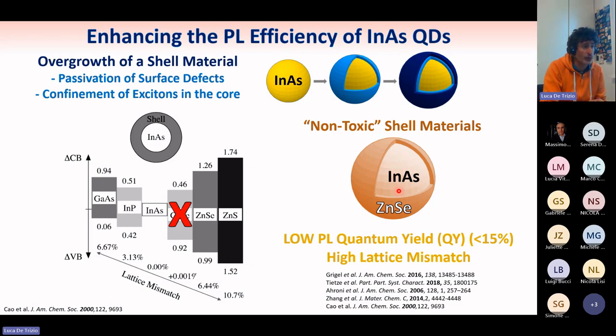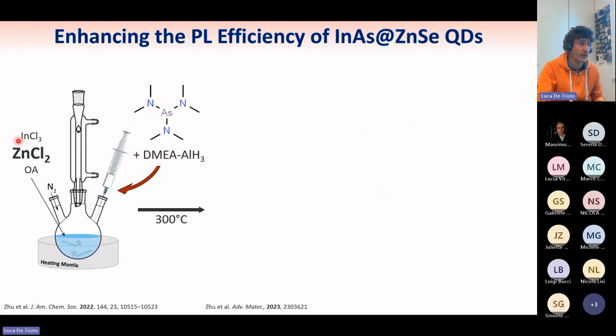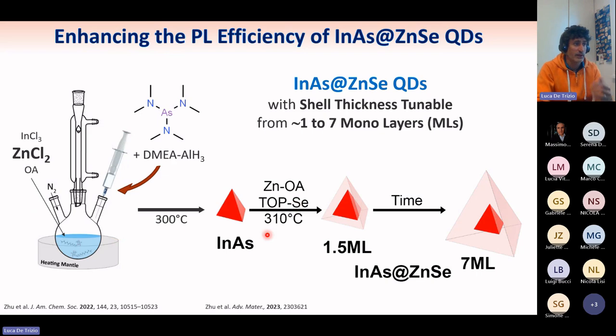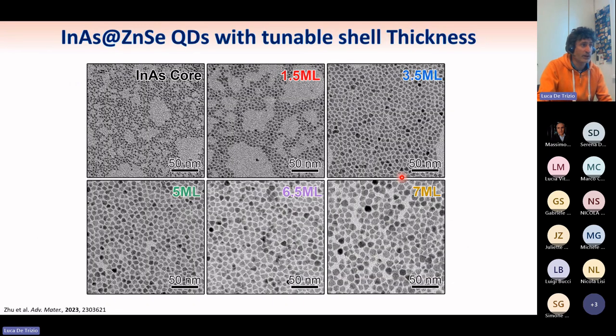So in the IEMAP framework, what we tried to do was to improve the efficiency of these systems, employing our new synthesis approach based on the addition of this zinc. So here you see the schematic picture of our synthesis approach. And with that, we got first indium arsenide quantum dots, and then we grew a thicker and thicker shell from one monolayer, so like one layer of zinc selenide, up to 7 monolayers of zinc selenide. So if we check now the TEM picture of these dots, you can see that they are relatively small at the very beginning of the synthesis. This is just pure indium arsenide. And then we grew the shell larger and larger. So you can see that the size increases by the overgrowth of our shell material.